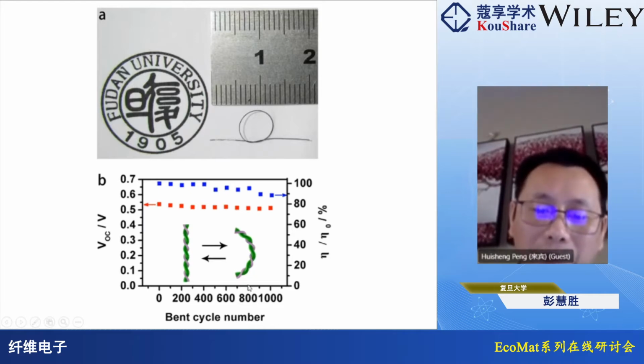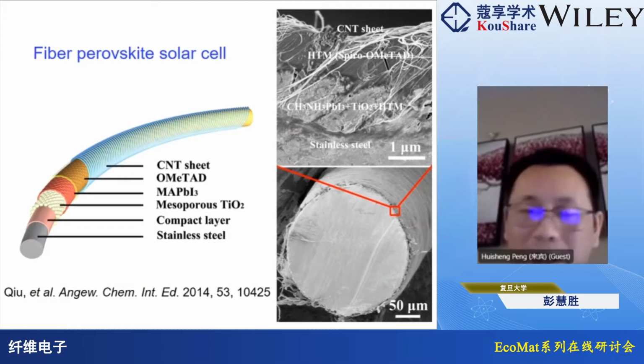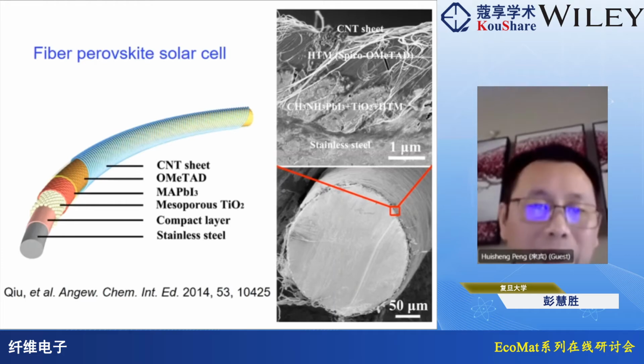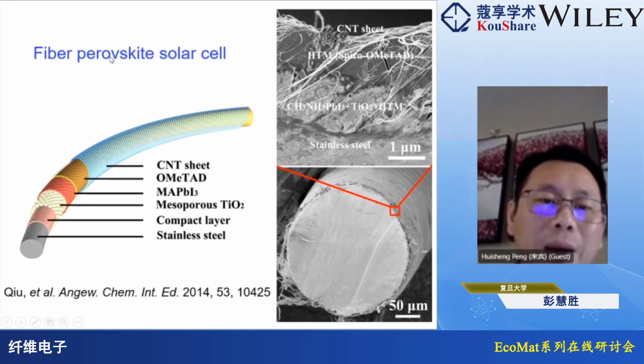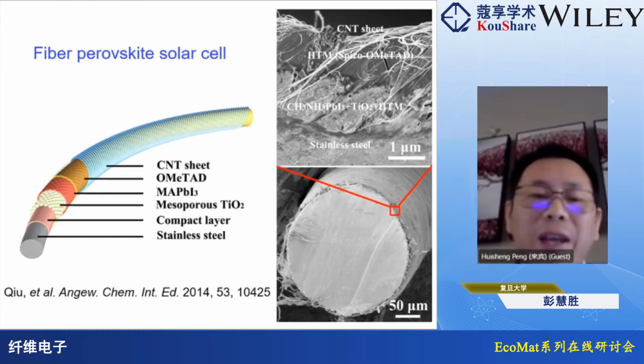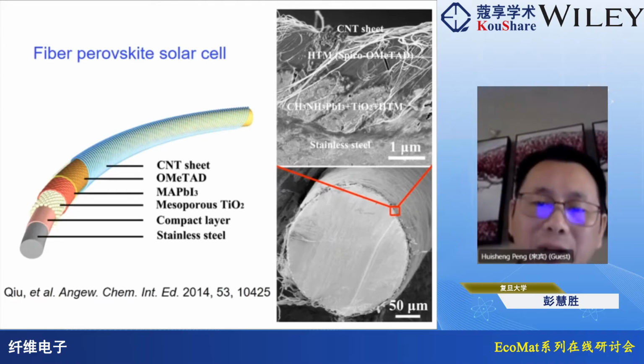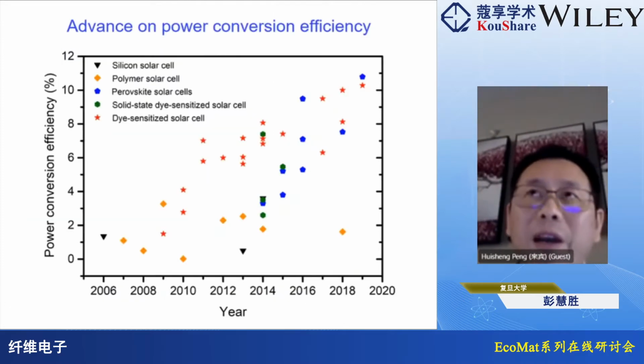And after bending 1,000 times, the power conversion efficiency can be maintained at 90%. And of course, for the polymer solar cell, the problem is that the power conversion efficiency is relatively low, although it's flexible. So then we come back to this perovskite solar cell. Many people are doing this kind of study, and we try to make them into fiber, and we expect it can show high power conversion efficiency, and it can also be flexible. And indeed, we can get a very high power conversion efficiency.